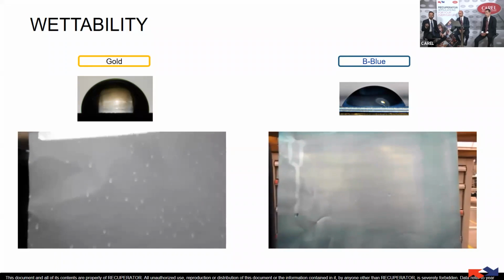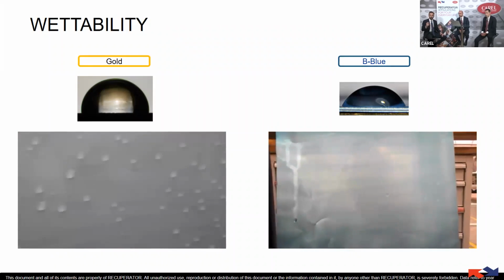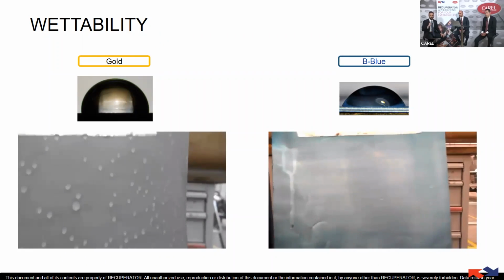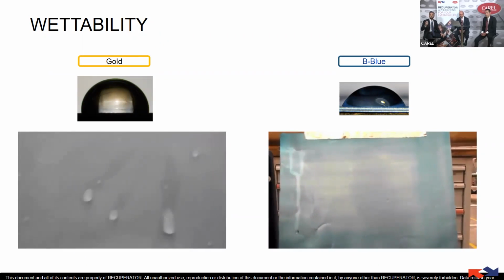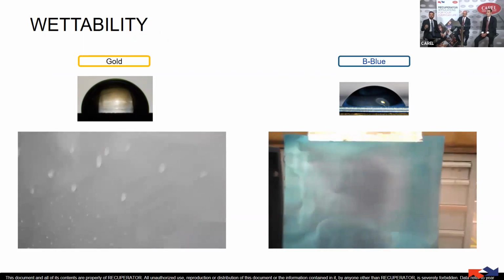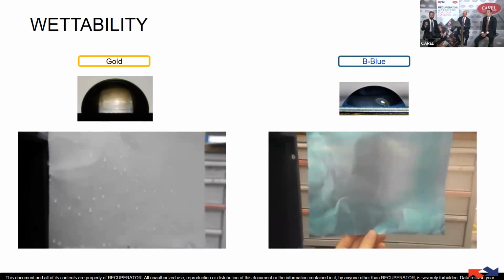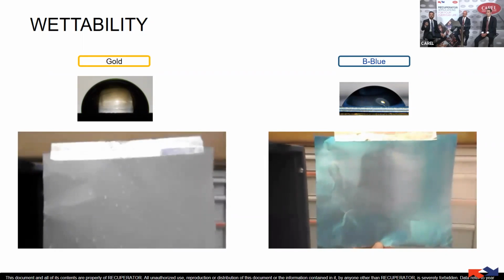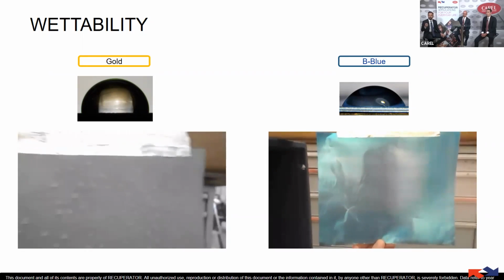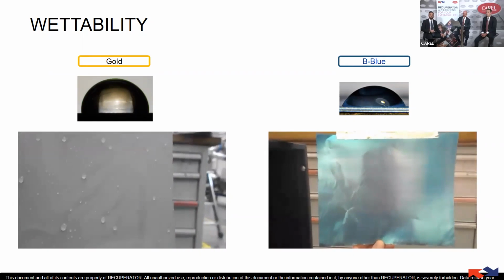If you see the second video, and you wait 5 seconds because it's a little bit longer, you can see when we spray water on the surface, we create an even film of water. It's impossible to see the droplets on the surface because it's just a film of water.